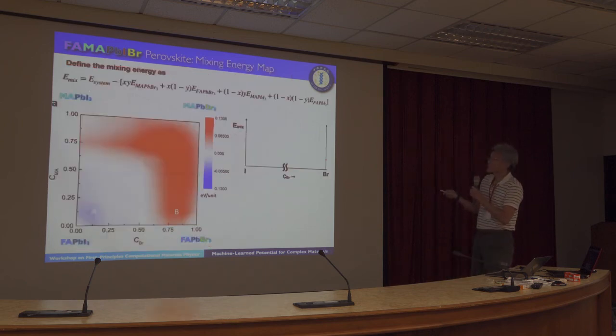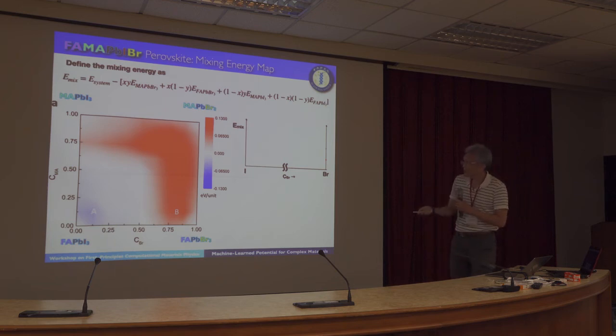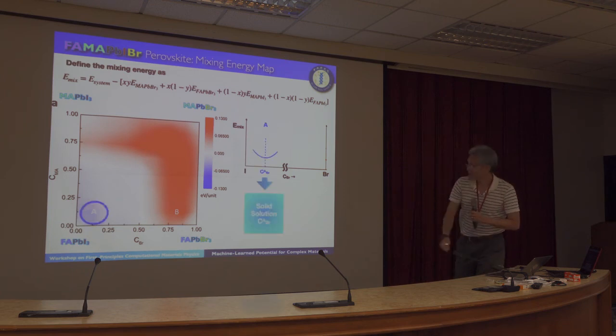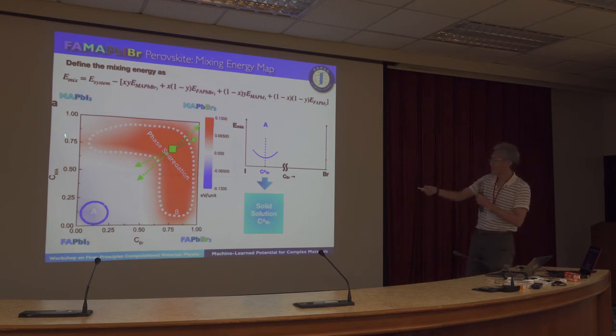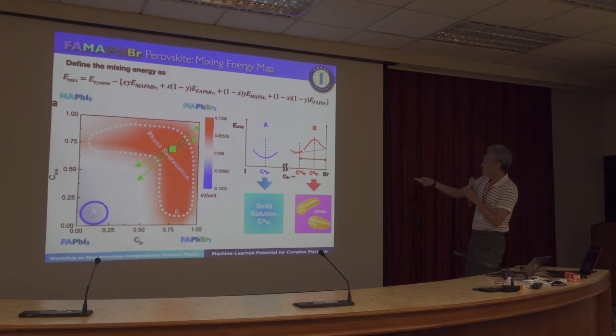Okay, so now we can compute the mixing energy. So this is the map of the mixing energies. You can find that in the concentration region A, what you would expect is that the energy landscape looks like this, and you would anticipate that in this region you have a solid solution with a bromine concentration C. However, in the region B, you would anticipate that phase segregation might happen, which looks like this. So the energy landscape in B looks like this, and the system can actually drop to a lower energy state by segregating into this phase and this phase. So you would anticipate that here the system might comprise 2 different phases.